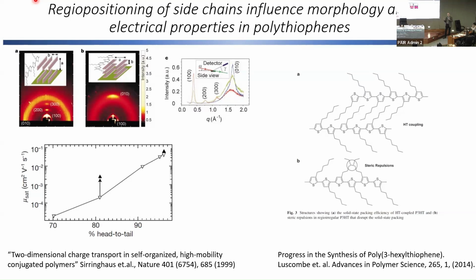And what they neglected to think about was the role that these side chains have on the self-assembly of these polymers from solution. So it's just kind of taken for granted that these were inert components of the polymer. But in actual fact, we can see when Henning Sirringhaus's group looked at what's called the head-to-tail regioregularity. And what that means is that this alkyl chain has two choices of where to be to connect to the next thiophene ring. It can be, in this case, in the tail position with respect to this thiophene, or it could have been here in the head position.